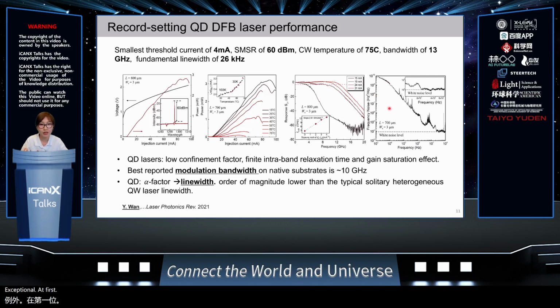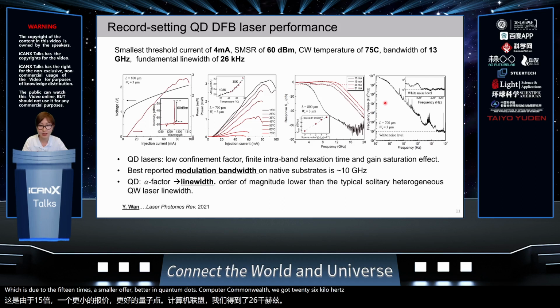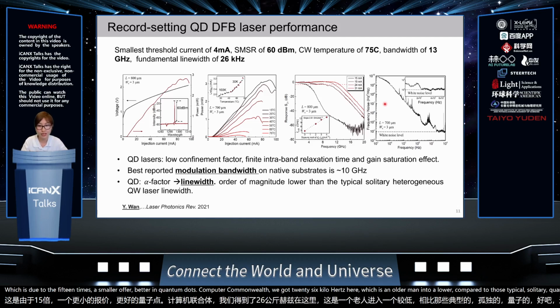And for laser linewidth, which is closely related to the alpha factor, which is 15 times smaller in quantum dots compared to quantum wells, we got 26 kilohertz here, which is an order of magnitude lower compared to the typical solitary quantum well laser linewidth, which is several megahertz.